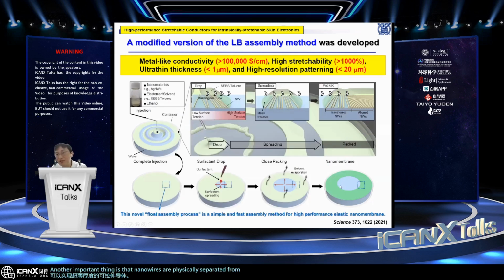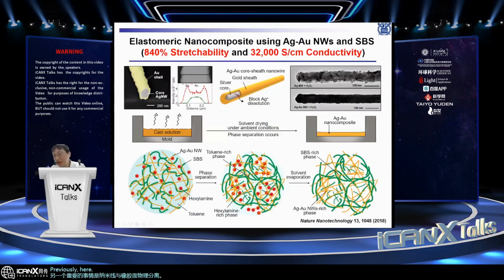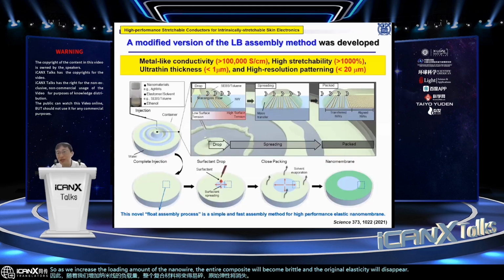Another important thing is that nanowires are physically separated from rubber phase. Previously, nanowires were randomly mixed with rubber. So as we increase the loading amount of the nanowire, the entire composite will become brittle, and the original elasticity will disappear. But in this case, nanowires are physically separated from rubber. So SEBS rubber can maintain its original elasticity. So original high stretchability over 1000% can be achieved.